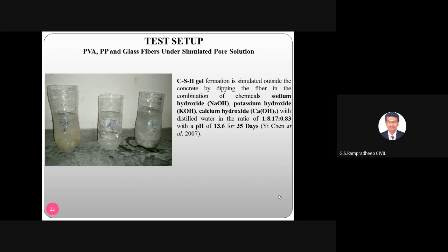That solution combination is sodium hydroxide NaOH, potassium hydroxide KOH, and calcium hydroxide Ca(OH)2, with distilled water in the ratio of 1:8.17:0.83. The balancing of pH at 13.6 for 35 days he is observing, right? So based on the molarity, in the paper you have all the details, and he is getting that ratio, and based on that ratio he is filling that fiber inside that specimen, the glass tube, and he is observing for 35 days. So it is based on the 2007 publication.